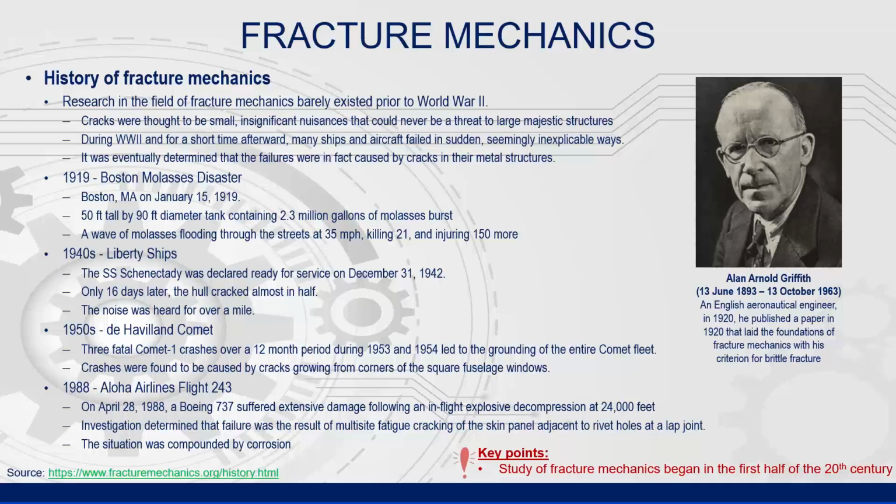On April 28, 1988, a Boeing 737 suffered extensive damage following an in-flight explosive decompression at 24,000 feet. Investigation determined that failure was the result of multi-site fatigue cracking on the skin panel adjacent to rivet holes at a lap joint. The situation was compounded by corrosion.